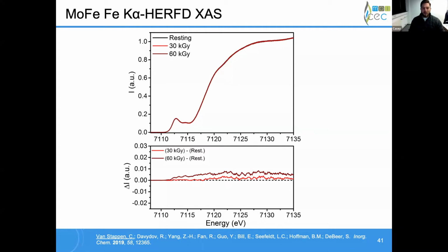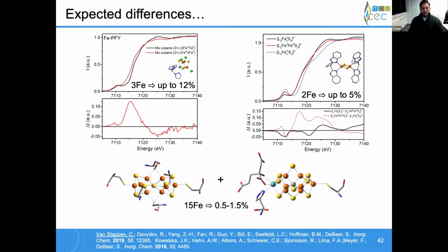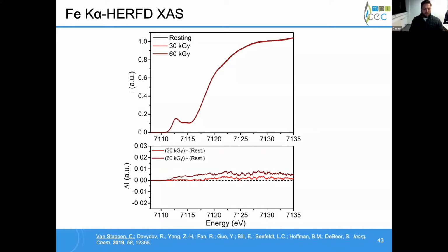And so the question is now, is this what we'd expect? If we look at the amount of difference that we're seeing from either the cubane or from this dimer, it's on the range of like 10 to 15 and about 5%. And so if we calculate back and you consider that we actually have 15 total iron in MoFe protein, then what we're observing is not that ridiculous. 0.5 to 1.5%. Yeah, we're more on the 0.5% side, but it's not unexpected. The question then is, are these changes significant at all? And so this brings up the question of how do you determine, or what's a good way of determining significance in a K-edge X-ray absorption spectrum.